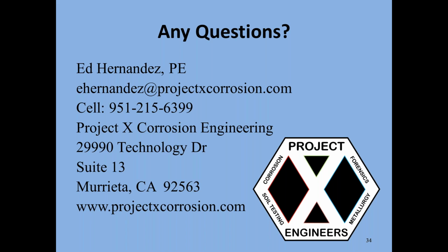So, yeah, it's a tough one, but basically we usually use a mixture of AASHTO and Caltrans corrosion rate estimations for corrugated steels and some other corrosion rate estimations based on the 40-year study from the National Bureau of Standards and the Romanoff books to come up with a mixture of potential estimated corrosion rates for the zinc coating and for the steel substrate.